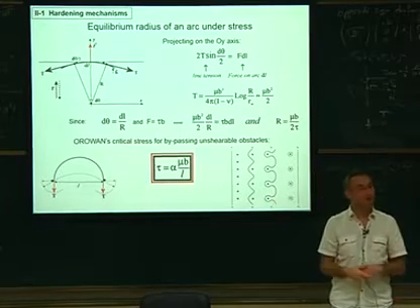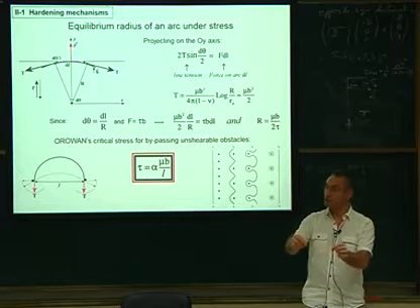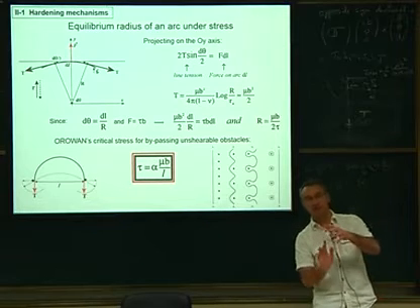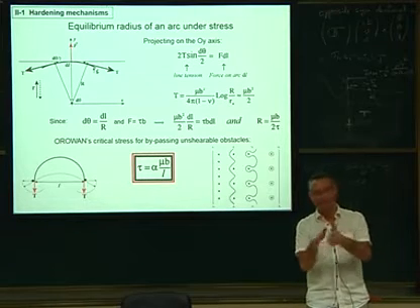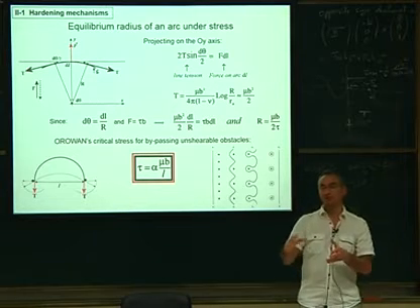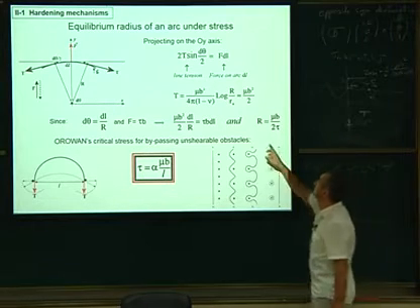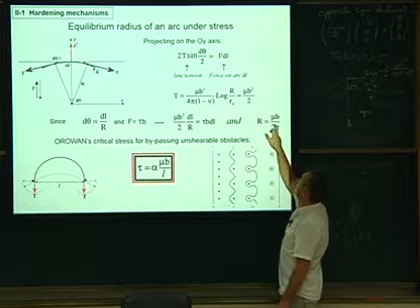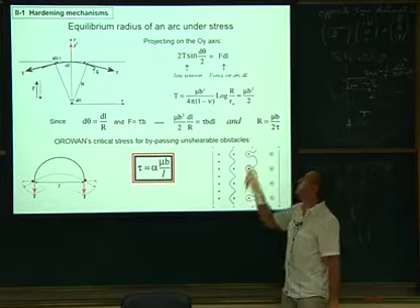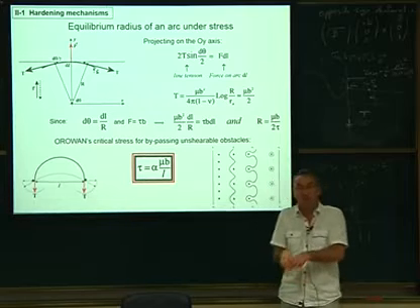And this is very important for TEM, as I said, because when they take a picture of their dislocations, they see the curvature naturally. There is this 3D effect. We saw this morning that you don't know if your dislocation is like that or like this. So of course, because of the projection, the curvature may be modified slightly. But at least if you have a given curvature in TEM, you can have an idea of the stress. You know that the curvature is inversely related to the stress, so it gives you an idea of the local stress you may have.